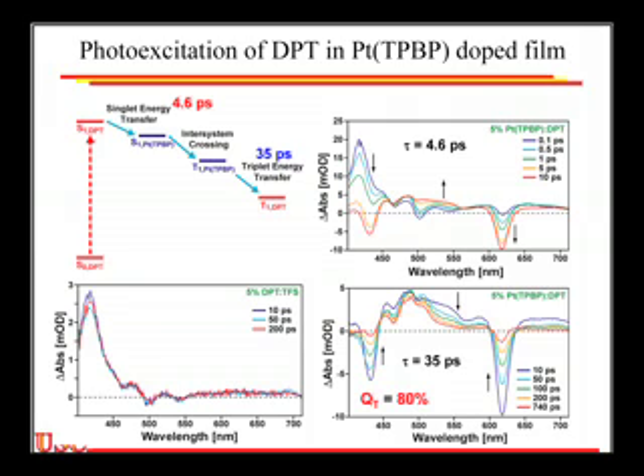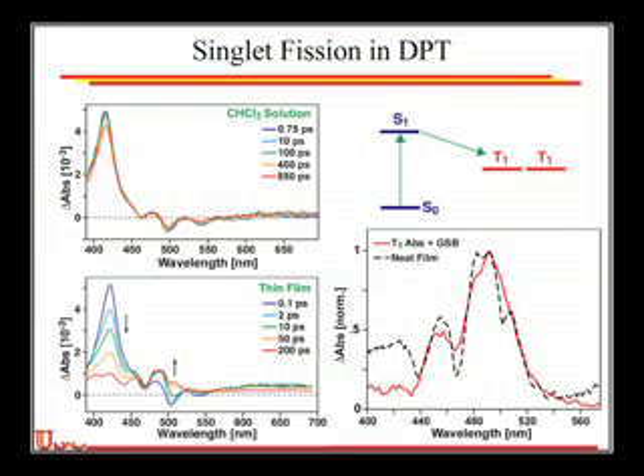But what if there's no platinum porphyrin around? So this is what I get in chloroform solution. If I put it into a thin film, there's no platinum porphyrin in this film. So I can see my singlet absorption decays. I get growth of a new species here, and this is all happening on pretty short time scales, on the order of a few picoseconds, when I'm getting decay of this peak and growth of another signal. I can pull this out again, and guess what? If I pull this out and correct for the singlet absorption, which I can get from the top curve, it exactly matches the triplet. So DPT is making its own triplet.